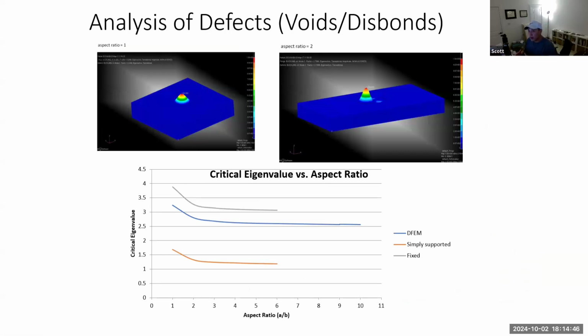So here we have a FEM with 3D elements that represent the core, and then you have 2D shell elements that represent the face sheets. Then you mimic the disbond by disconnecting the nodes of the shells from the core elements, so they are not connected in the disbond zone. And then you run your FEM with the loads and you determine if that area of disbond is going to buckle under that load and boundary condition. And you determine the buckling eigenvalue.